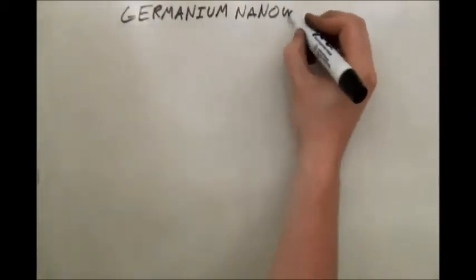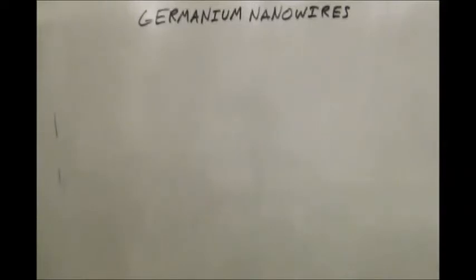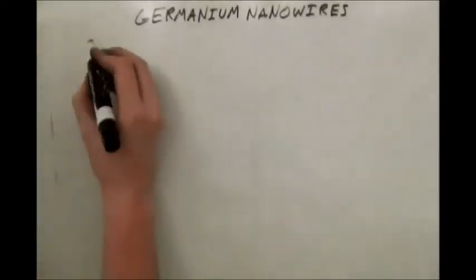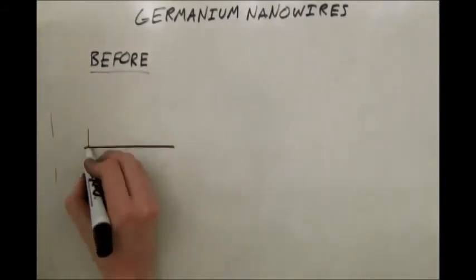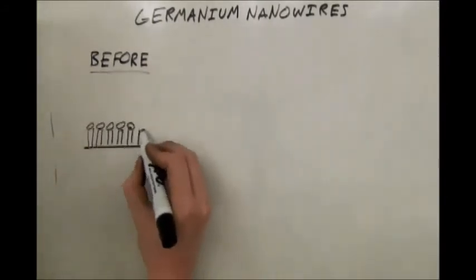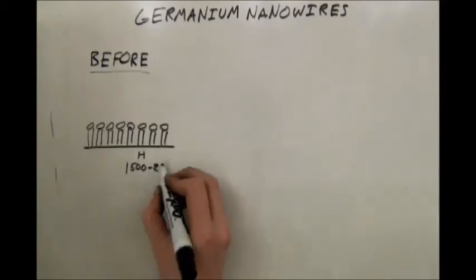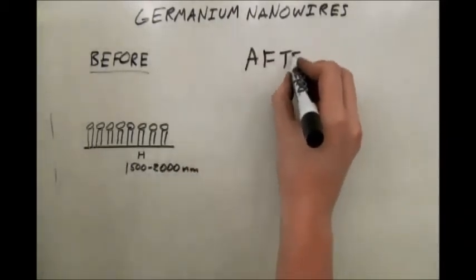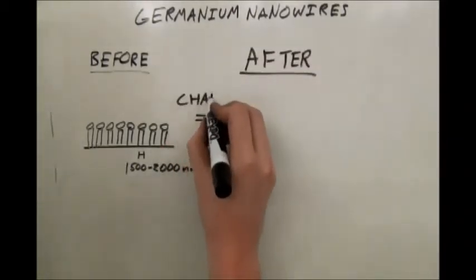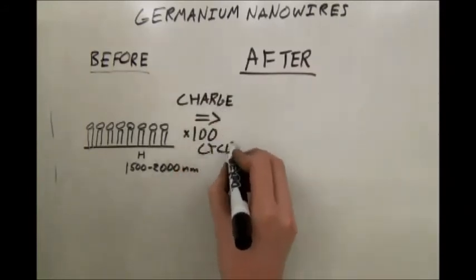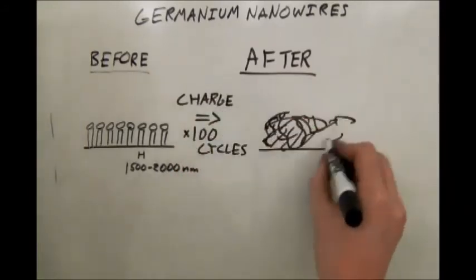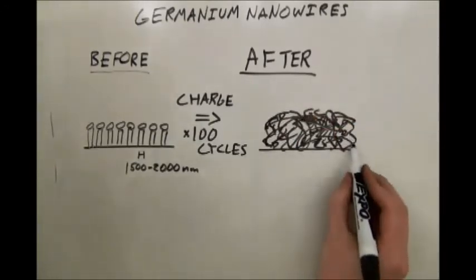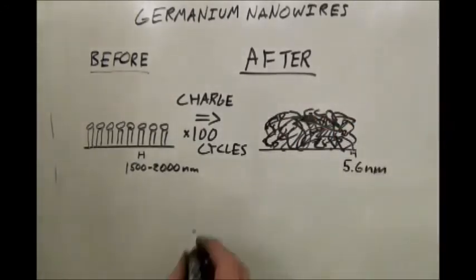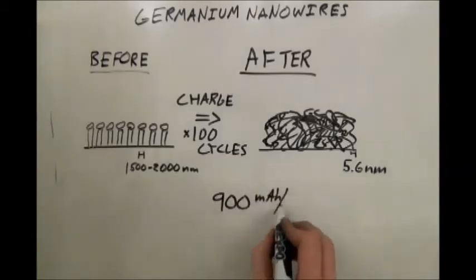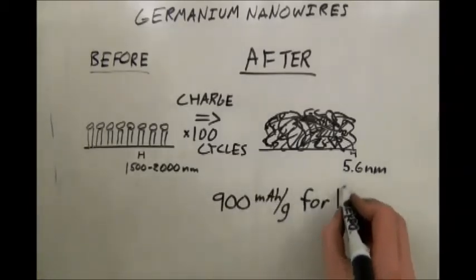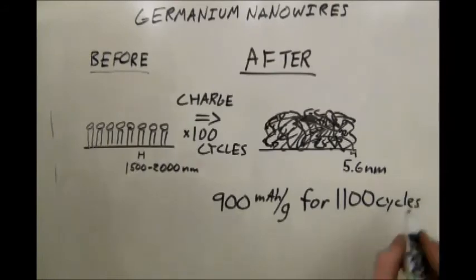Nanowires can expand and contract without destroying themselves, unlike a flat plate anode of the same material. Germanium nanowires have an especially interesting characteristic, as they tend to destroy themselves in a very slow, consistent, and positive way. Starting out with vertical stalks of wire that are 1,500 to 2,000 nanometers in diameter, the anode slowly transforms over the course of 100 cycles into a stable, porous network of millions of much, much smaller nanowires. This structure is able to maintain a charge capacity more than double that of even the most efficient lithium-ion battery for over 1,100 cycles.